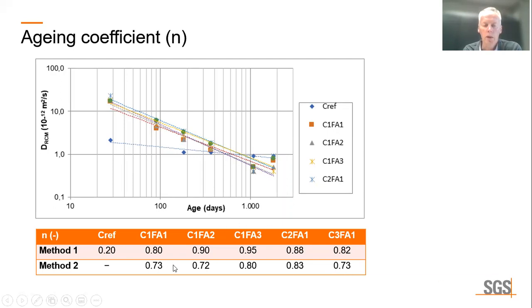If we then look at the aging coefficients derived by this method, we see that we have values of 0.7 up to 0.8, and that the 5 fly ash concrete mixes show quite comparable results.